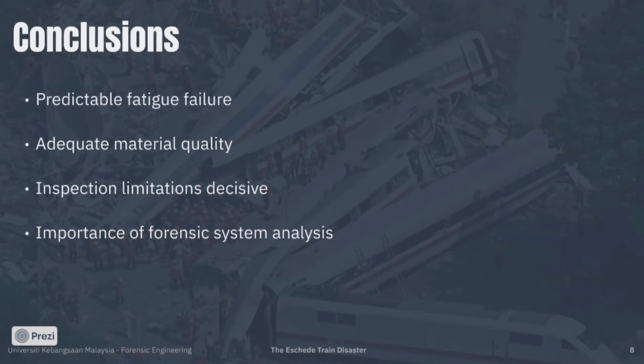To conclude, the Eschede accident demonstrates that catastrophic failures rarely come from a single defect. Material quality was adequate and there was no evidence of manufacturing defects at the crack initiation site. The failure developed as a predictable fatigue process under normal service loading, with long-term crack growth at an internal location. The disaster occurred because the damage remained undetected due to inspection limitations and was compounded by organizational decision-making and delayed response to warning signs. The core forensic lesson is to analyze the whole system: component, design, inspection capability, and organizational process.